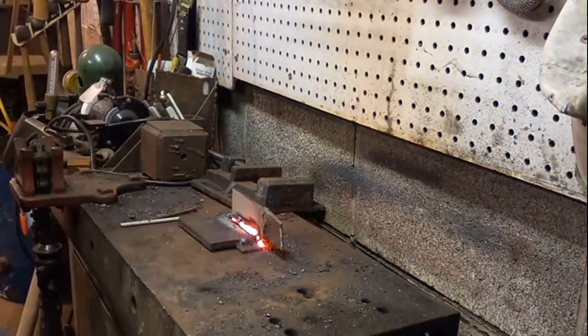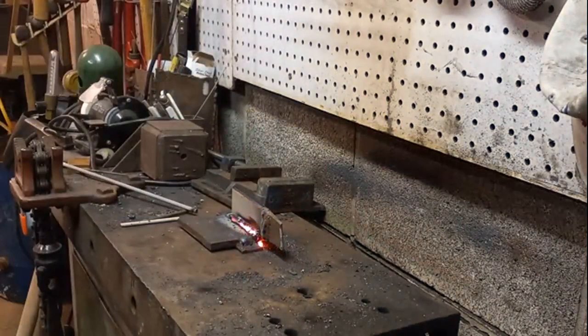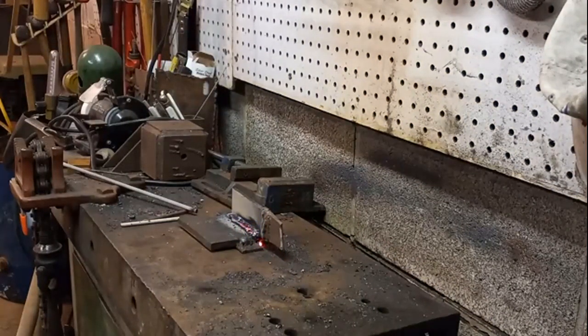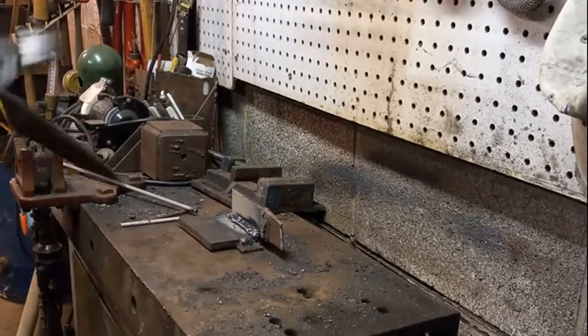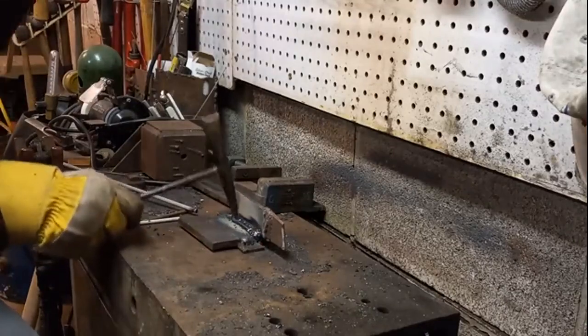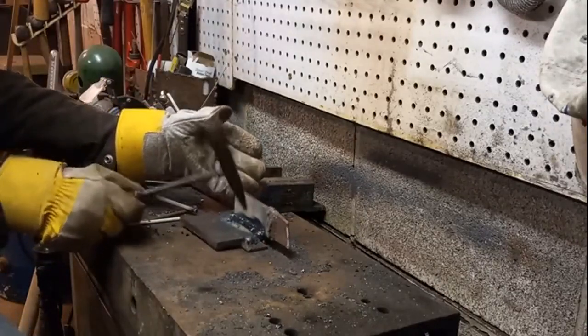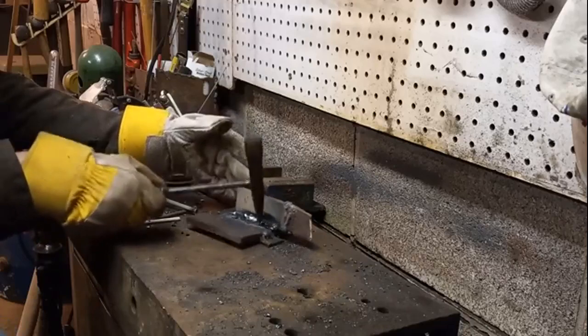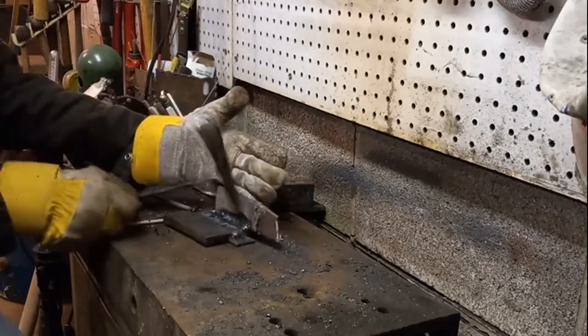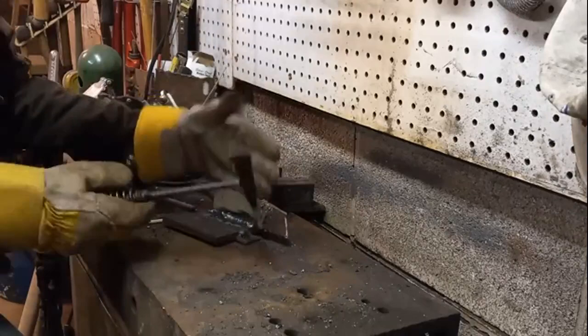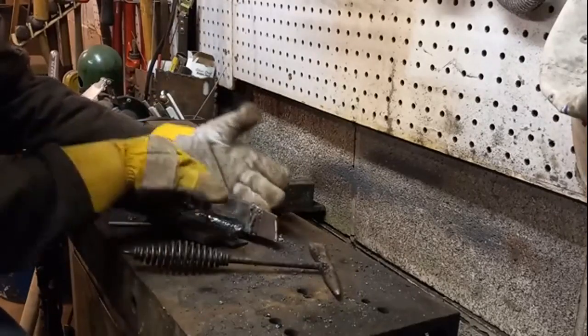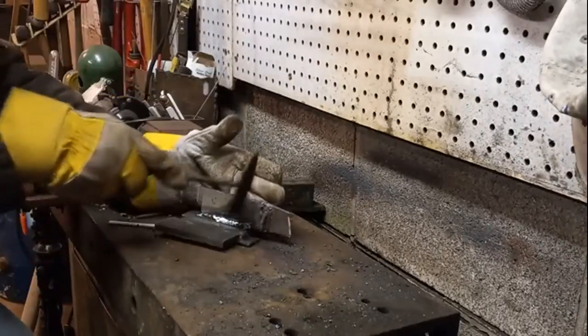I have a feeling that didn't go real great. This is why I dislike E6013 type rods so much, because there's so much slag in that puddle. Even when it's still liquid moving around, it's almost impossible to see your puddle. It's just enveloped by slag all over the place. What do I got? See, after I got past that first little bump there, it looks fine. But in the beginning, I knew I wasn't going to have a good bead.